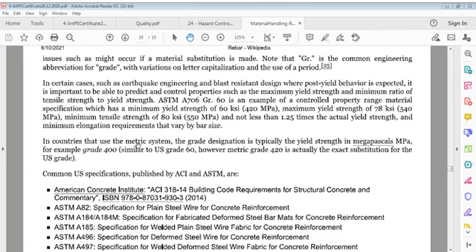In certain cases, such as earthquake engineering and blast resistant design, when post-yield behavior is expected, it is important to be able to predict and control properties such as maximum yield strength and minimum ratio of tensile strength to yield strength. ASTM A706 grade 60 is an example of a controlled property range material specification which has a minimum yield strength of 60 KSI, 420 MPa, maximum yield strength of 78 KSI, 540 MPa, minimum tensile strength of 80 KSI, 550 MPa and not less than 1.25 times actual yield strength, and minimum elongation requirements that vary by bar size.